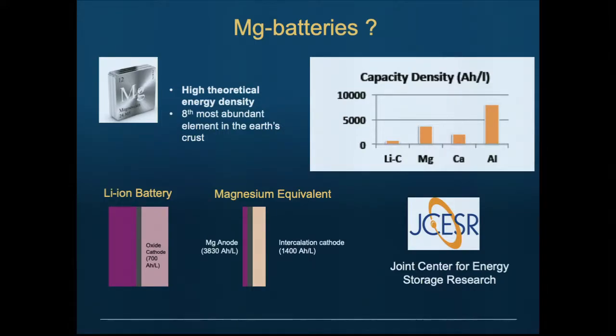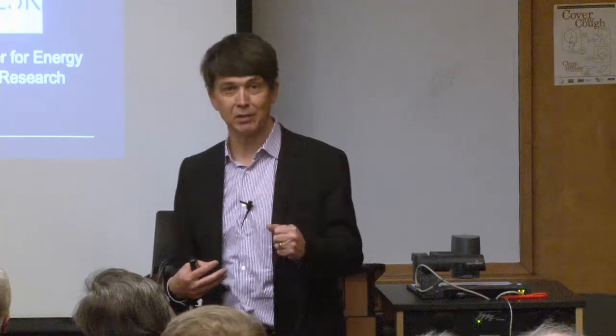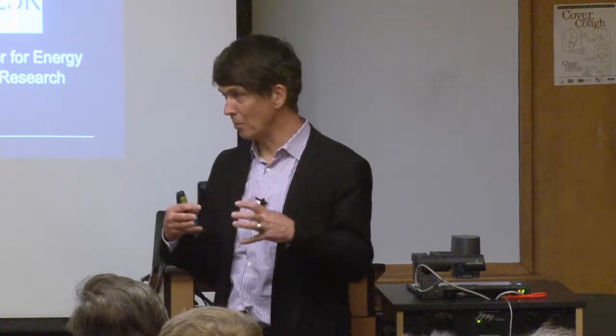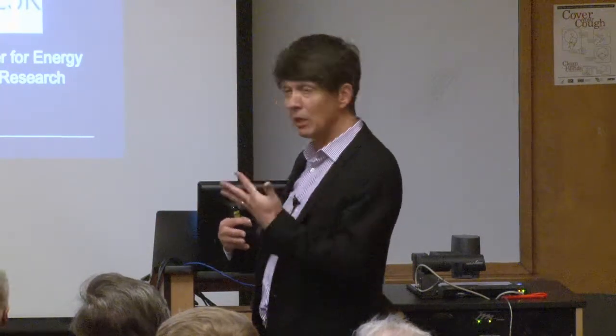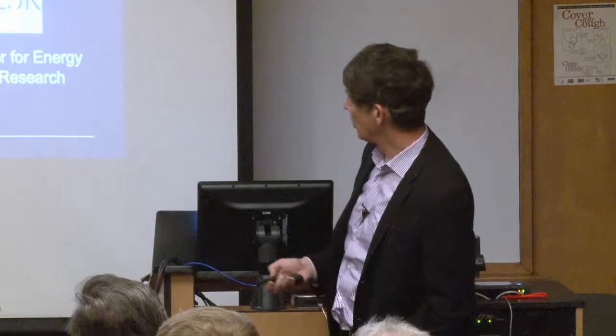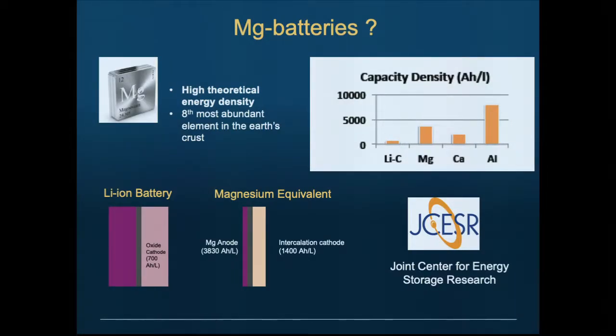A good cocktail party story is that the density of magnesium ions in magnesium oxide is higher than in magnesium metal, right? It's such a densely bonded material that there's almost no point defects, you can get nothing through. So the magnesium anode is extremely passivated. But it has enormous charge density, right? If I take an equivalent lithium anode and I now take the magnesium equivalent in terms of the amount of charge, you see it gets super thin. So in principle, in terms of energy by volume, which is, by the way, the criterion that most applications care about, not energy by weight, magnesium anodes would be enormous.